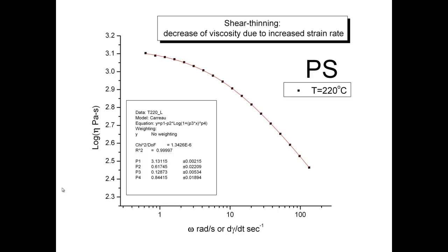The log of viscosity is seen to have a plateau at low speed, low omega, which is the frequency in a dynamic test, or gamma dot, which is the derivative of the strain, so the strain rate, if you want, which relates to the throughput or the speed at which the layers are moving in the flow directions. This is a classical view for someone who is in rheology, and the Carreau equation describes this pretty well. The plateau is the Newtonian viscosity on the left hand side, and the material shear thins, meaning this viscosity decreases as we move towards a higher strain rate.